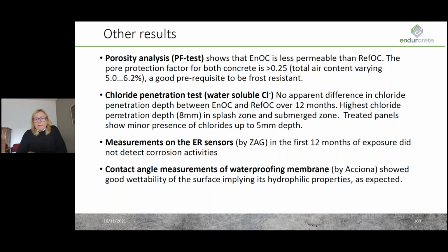So generally, the EnDurCrete offshore concrete had a lower permeability than the reference concrete, and the total air content was varying between 5 and 6%, which is a very good prerequisite to be frost resistant. Chloride penetration tests showed no apparent difference in chloride penetration between the offshore reference and offshore EnDurCrete concrete after 12 months. The highest chloride content was measured in the splash zone and the submerged zone.